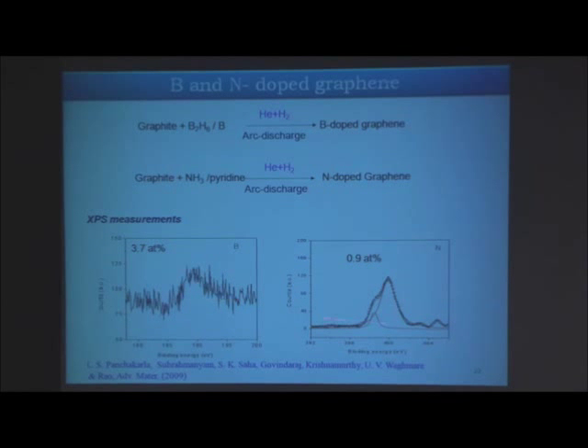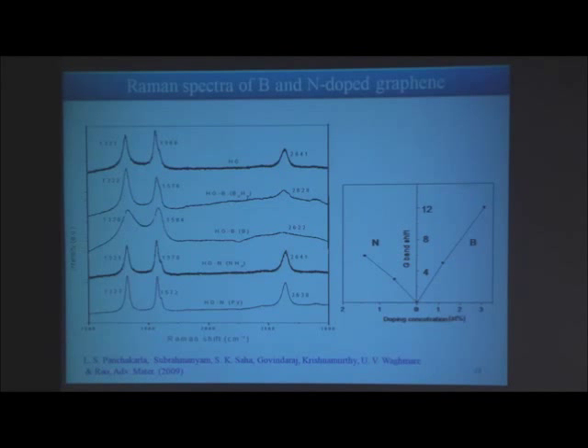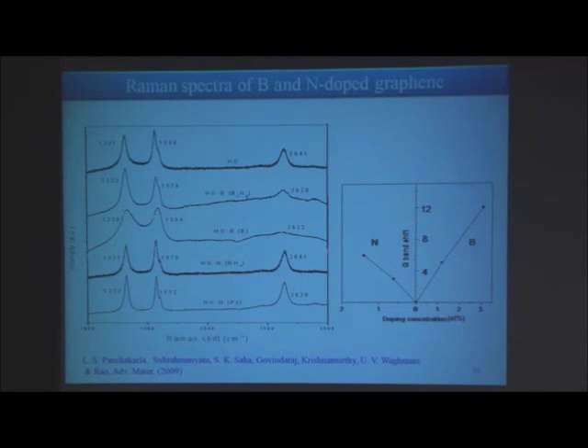Unfortunately, XPS is not very good. You have to do EELS in the electron microscope, and we could estimate how much nitrogen and boron. Well, ignore all the spectra, that is not important. What is important is here, the curve: the amount of nitrogen, that is N doping, and the amount of boron, P doping, both again increase the G band frequency, stiffening of the G band.